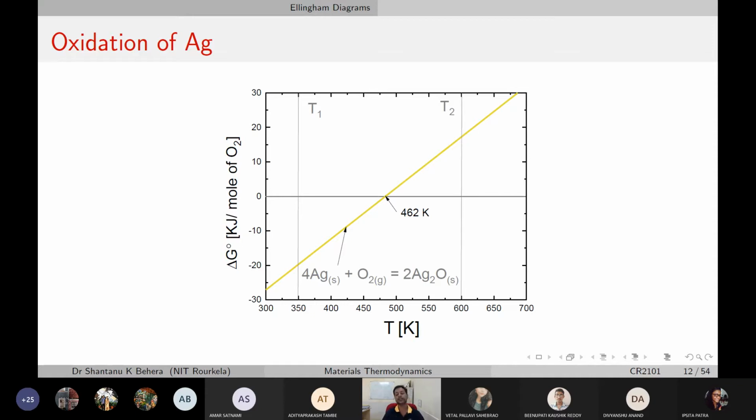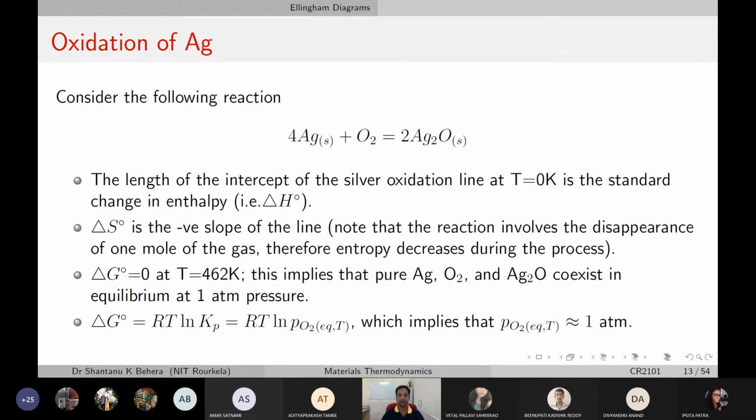And the entropy change, when you normalize it with the reaction of 1 mole of oxygen, all of these are going to be almost parallel to each other with subtle variations, of course, but by and large they're all parallel to each other. That's what is called the Ellingham diagram. But in the same diagram, on the bigger scales, you'll have all those oxidation diagrams plotted together on one plot itself, right?